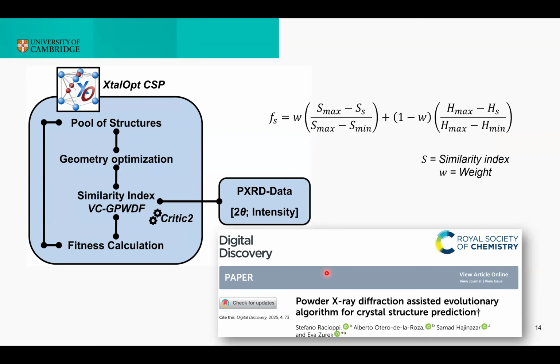So this routine is now implemented in XtalOpt, and the workflow looks basically like this. Once we generate the new structures and we optimize them with DFT, the calculation of the similarity index happens at this stage. And the powder diffraction data that one can use is basically just a list of 2 theta angle values and the relative intensity. And this can be just a list, so there's no need for the indexing. Moreover, the list can also be non-continuous. So what I mean is that this list can be also just a short list of the main peaks that one wants to consider from the diffractogram and not the entire pattern.